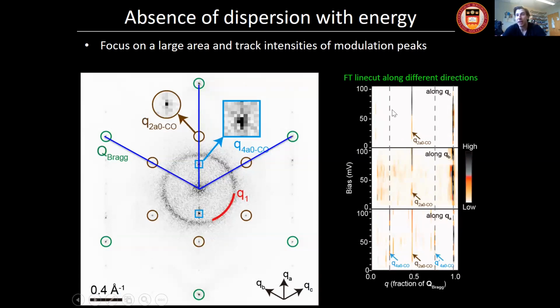What I'm showing here on the right, on the y-axis, is energy from 0 to 100 millivolts for the 3 directions, QA, QB, and QC. What you will see for each one of them is this non-dispersive 2a0 charge ordering wave vector, which is exactly what we would expect for a charge ordering nature of the state. And then for this one particular direction, we also see a very strong 4a0 peak that also does not disperse with energy.